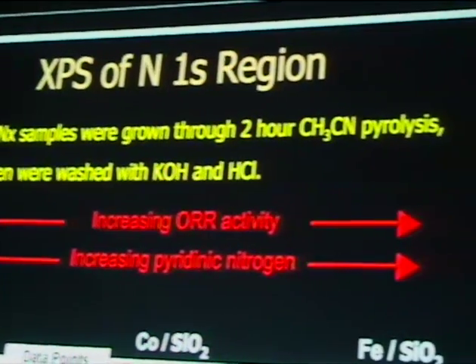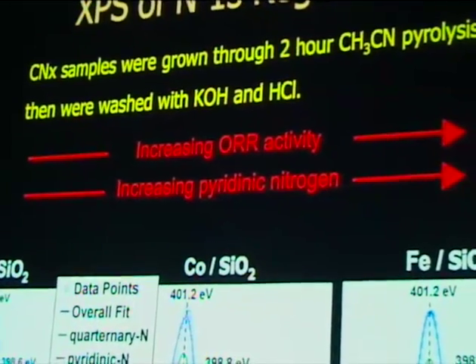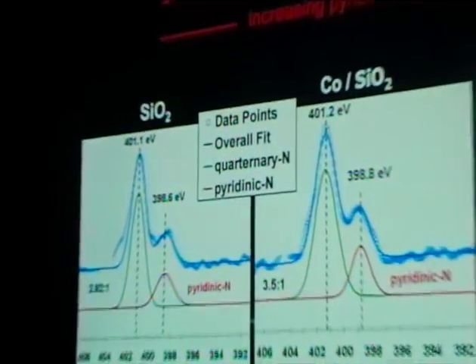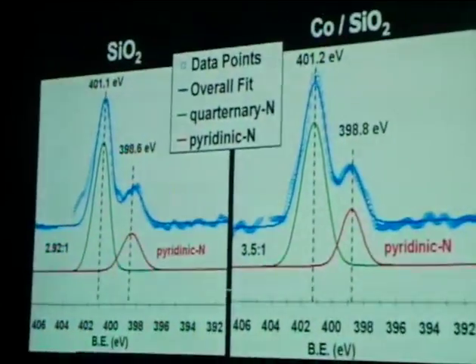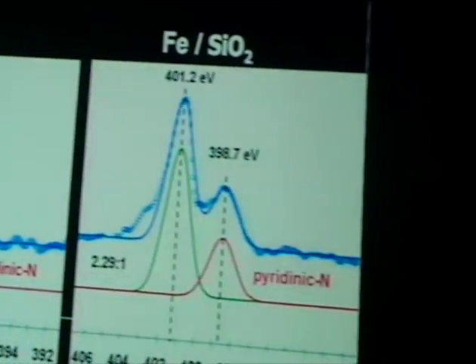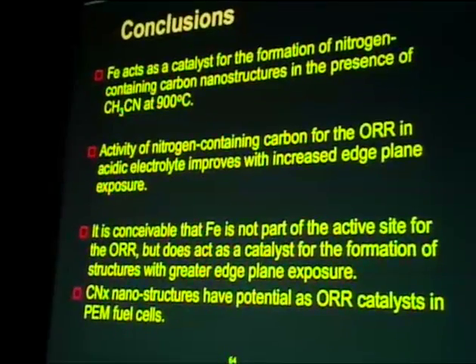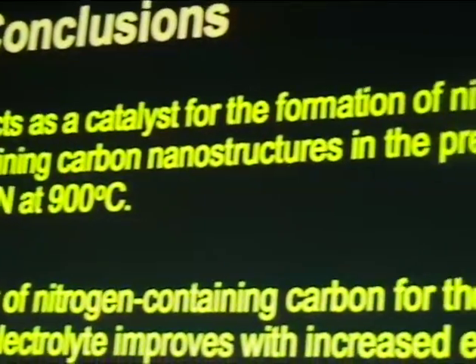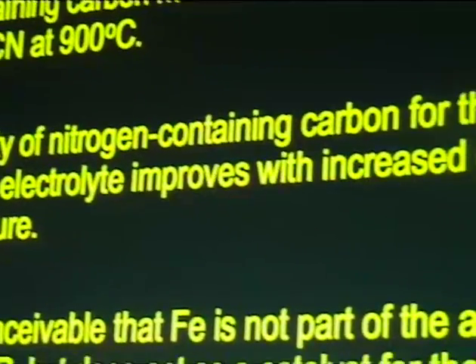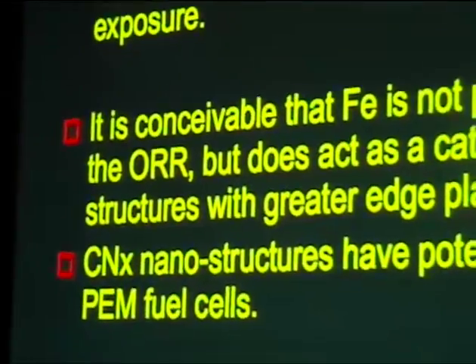Again, if we go back to our correlation and look at the catalysts which are grown on silica support, here's the direction that the pyridinic nitrogen is increasing, and here's also the direction that the oxygen reduction reaction is increasing. So just to quickly summarize, again, as I said earlier, Elizabeth is going to present a poster in the afternoon, and she'll talk more about the more recent work, especially about the potential of these materials as a catalyst for direct methanol fuel cell, which is really looking very promising.